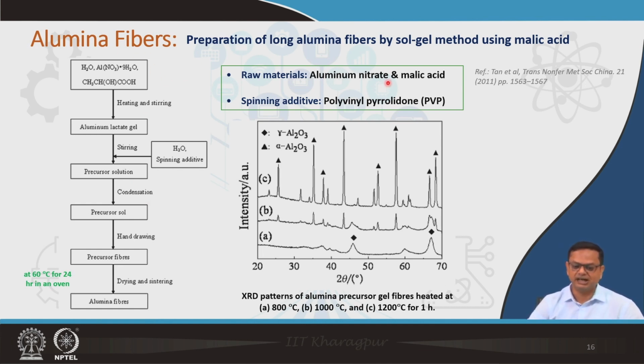For example, in this case the precursors are aluminum nitrate and malic acid, and again that goes through the steps of Sol-Gel. So, you go for gel making, okay, and then spinning is done to get the gel fiber or precursor solution, and then it goes through a condensation, and ultimately here it is actually getting hand drawn to get the precursor fibers, and then drying and sintering, which are called calcination, you get alumina fiber. And depending upon the calcination temperature, you can see here there are different temperatures like 800, 1000 and 1200 degrees Celsius, and you can see from gamma to alpha, ultimately at higher temperature of calcination you get better structure of alpha alumina.